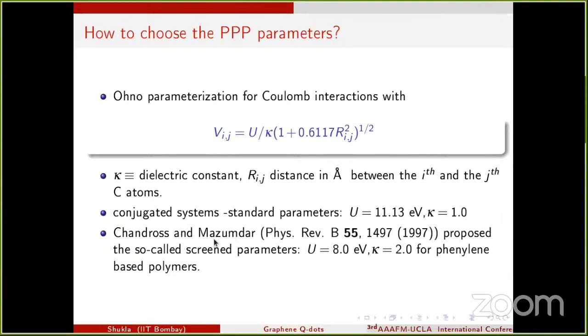However, Chandross and my collaborator Mazumdar in 1997 proposed a set of different parameters, and they are called screened parameters, and they work very well for any system with phenylene rings. Because graphene will have all these hexagons, I expect them to perform well for graphene quantum dots. So here U is taken to be 8 eV and kappa, the dielectric constant, is taken to be 2.